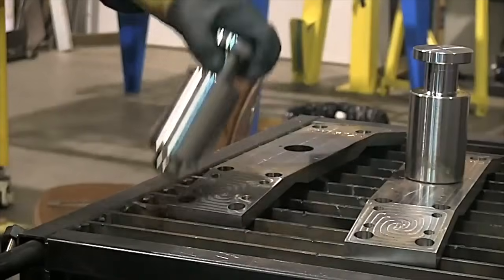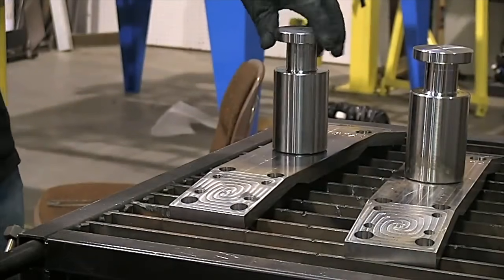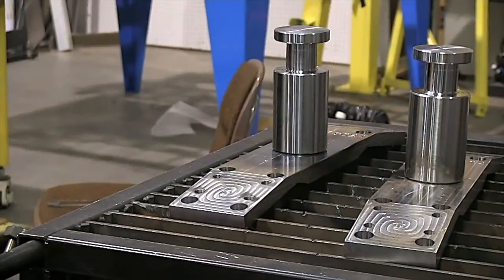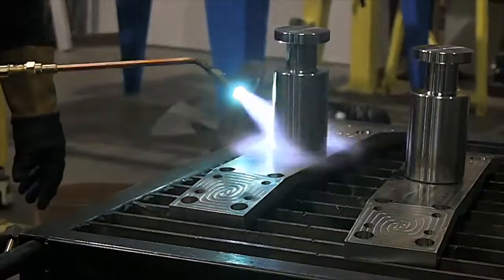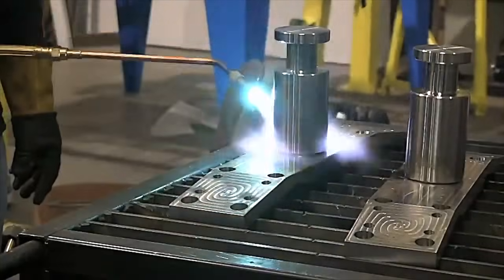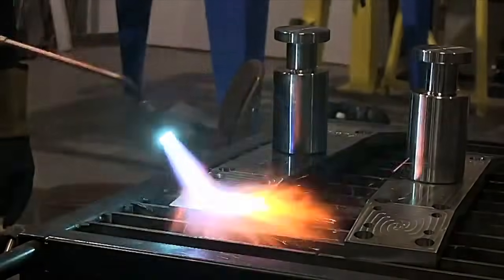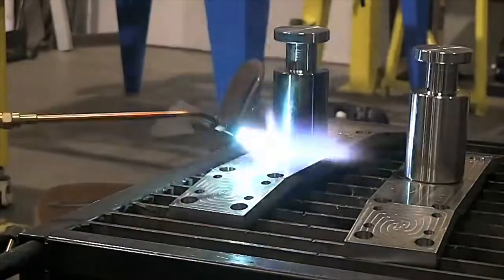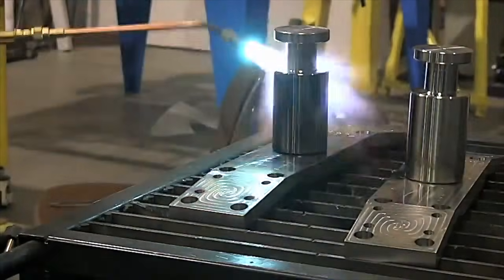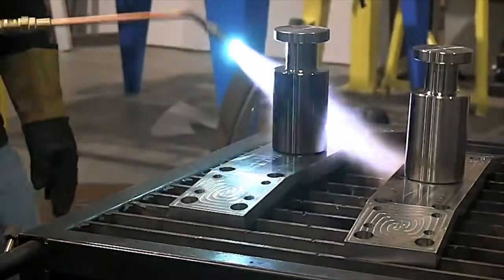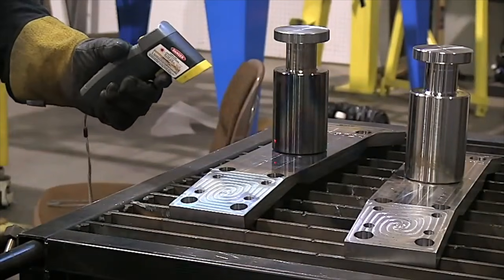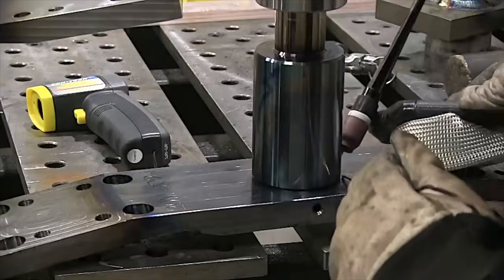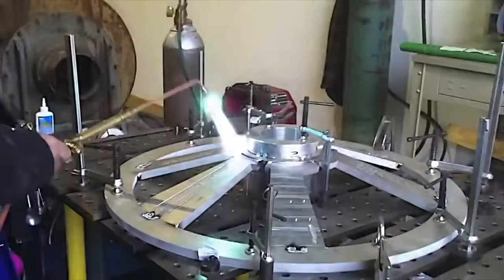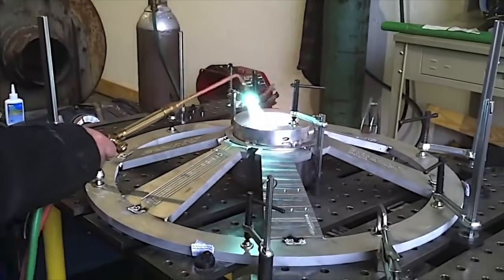Let's do it. One common practice for really thick carbon steel, medium carbon steel, and even low alloys like 4130 and 4140 is to preheat before welding. It's a good practice, it's a common practice. Sometimes it's required by a welding procedure, but that's to slow the cooling rate to prevent hardening and to prevent it from getting brittle.